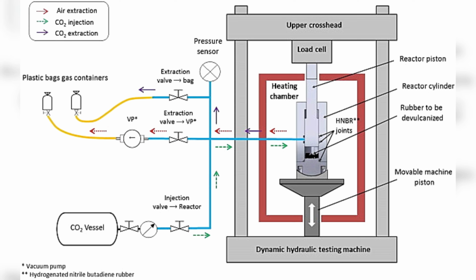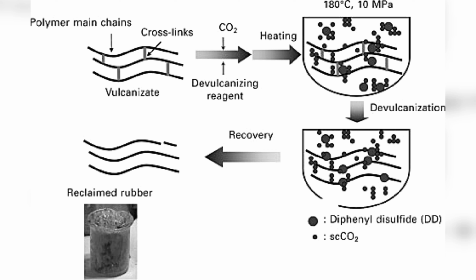There are multiple ways to achieve devulcanization, but one of the most commercially viable approaches is the supercritical carbon dioxide method, developed by Tyromer. In this process, ground tire rubber is mixed with supercritical carbon dioxide, which is a phase of CO2 where it behaves like both a gas and a liquid. In this state, the CO2 penetrates the rubber matrix and swells it, weakening the sulfur bonds. Under controlled conditions, the sulfur crosslinks are broken, but the main polymer chain remains mostly intact.